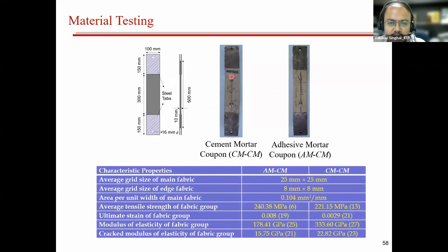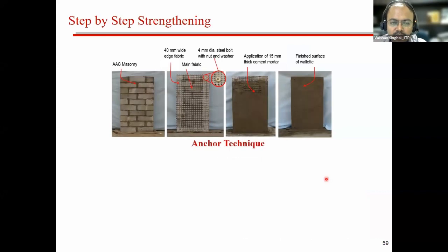In one case the fabric is embedded inside the cement mortar, so it is kind of a sandwich between both cement mortar, and in the other case, on one side it is adhesive mortar and on the other side it is cement mortar. We found nearly similar properties for both cases, so there was no significant difference between the adhesive mortar and the cement mortar.